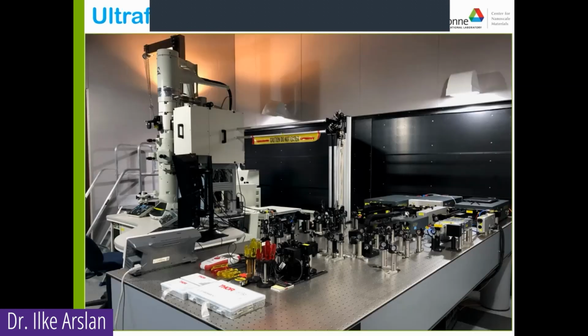There are femtosecond timescale lasers, obviously. So we use that. We use a femtosecond laser to come into the column, hit a mirror, and go up to the cathode. We photoexcite the electrons from the cathode, and they come down the column. And at the same time that the electrons hit the sample, well, just before they hit the sample, we photoexcite the specimen with a second laser. So then we have time resolution that is on picosecond to femtosecond timescales. And because it's a TEM, we have nanometer spatial resolution, and we can do imaging, diffraction, and spectroscopy to understand materials dynamics in non-equilibrium.